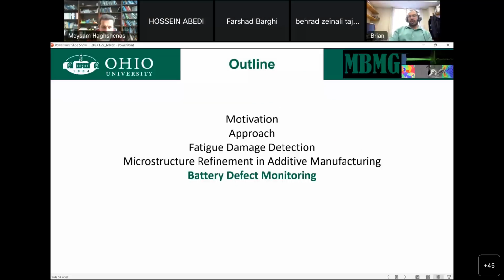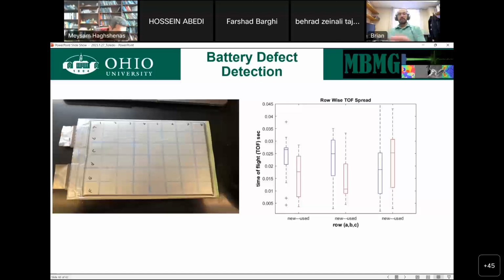And that leads into the battery defect monitoring, which is very quick, as we are just starting this, but I'd like to show that the methodology I talked about for damage detection, altering metal microstructure in additive manufacturing, can be used for almost anything you want. And in this case, we have batteries. And so we have 3 batteries that we're testing. One that is pristine. We got it and did not charge it maybe once, just to see the effects there.